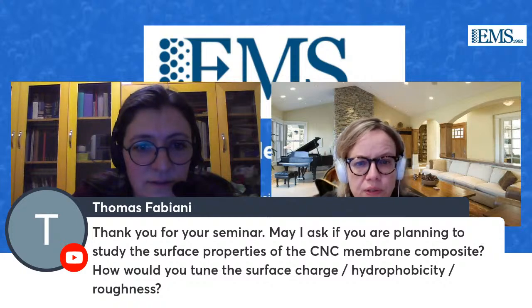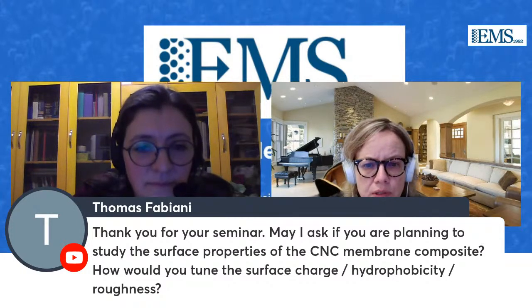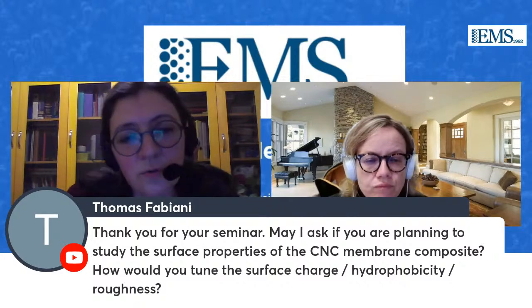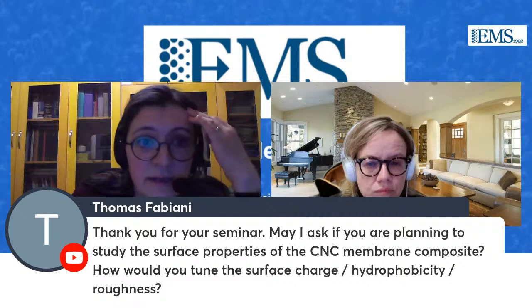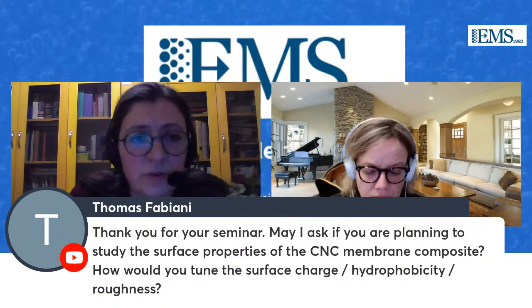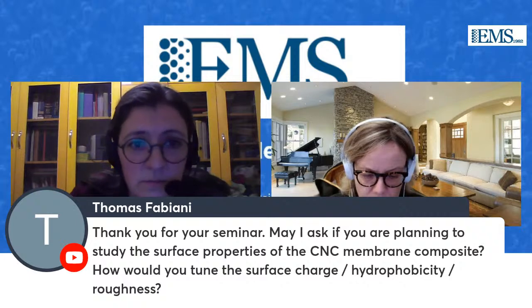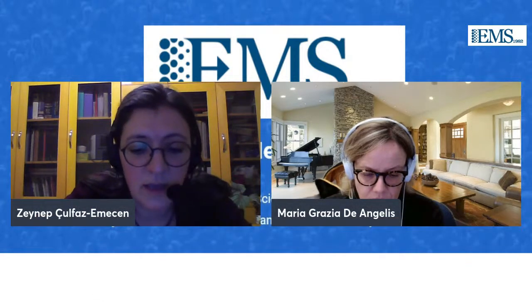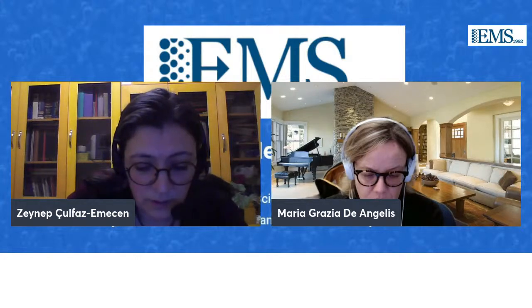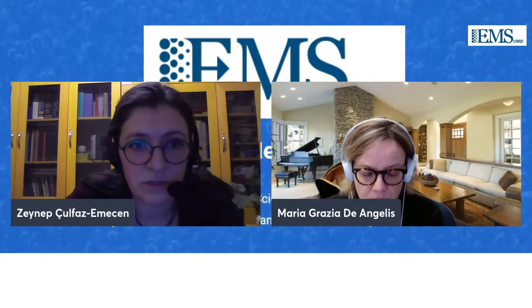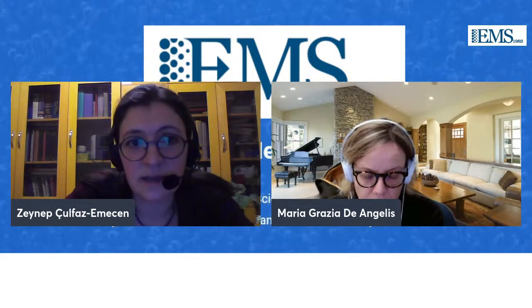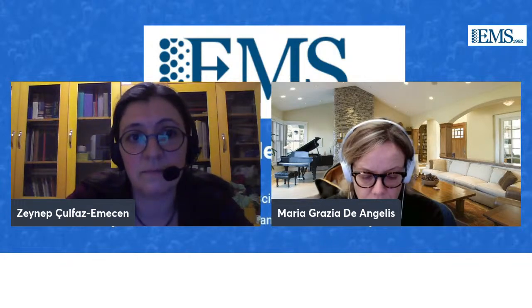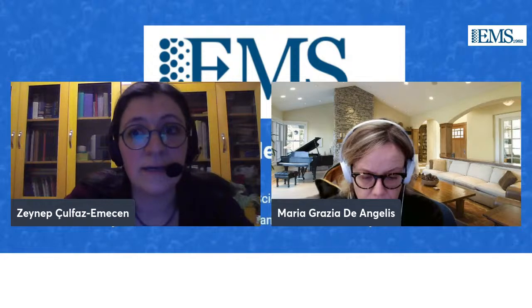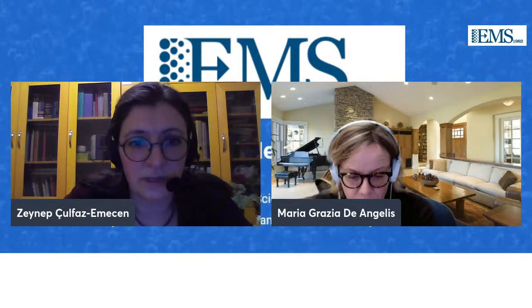Are you planning to study the surface properties of the CNC membrane composite, and how would you tune the surface charge, hydrophobicity, roughness? Well, the surface charge is simply a function of the CNC. Of course, it can be modified. That's also quite a good thing about cellulose. The hydroxyl groups are quite reactive, so you can modify them with many things. And the surface charge, again, you can modify with different groups. Hydrophilicity would be expected to be good with cellulose, even in its native form. It's quite hydrophilic. And then the roughness is again a function of how they deposit, and likely would change with the extent of alignment, for instance. But yeah, those are of course things to consider.